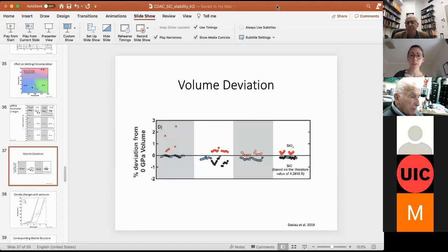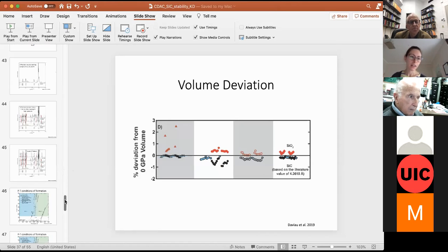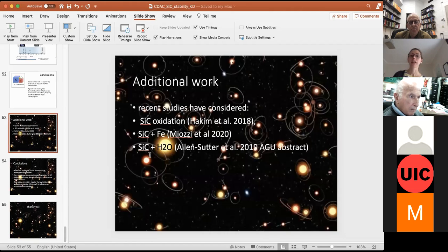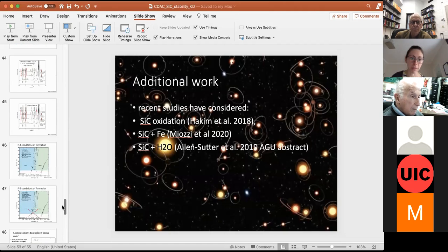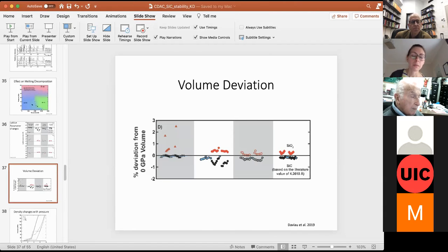So we did our best to dry the samples out as much as possible. Before compressing, we would always put the diamond cells in the oven to hopefully dry out overnight. So hopefully there isn't too much water present. One of those additional studies that I mentioned was an abstract from AGU last year that was looking at silicon carbide and water. I actually saw some indication of what looked like methane from this reaction. So if you have a lot of water, that might show up in the diffraction, maybe as a methane material, right?